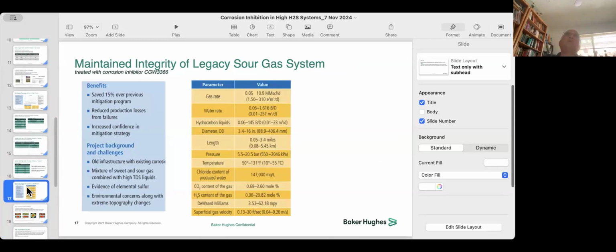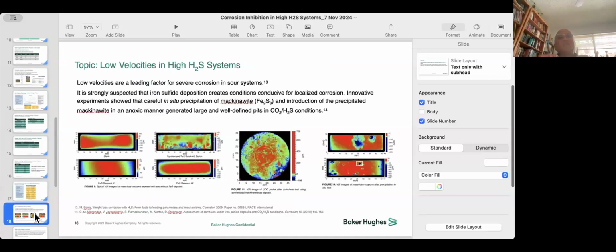The CGW3366 was extensively used in Canada, and it's used in Tengiz, or it had been used. Recently we changed this, but it had been used in Tengiz also, in the Kazakhstan fields, and we did a lot of work. Reproducing pitting corrosion is very difficult, and in fact, in the project that created this, we had to spend a year to reproduce the pitting corrosion and figure out a method of producing it. Once we found a method, you then test a whole bunch of things. And we found out what would be a very, very popular inhibitor all over. So again, low velocities are the leading cause.